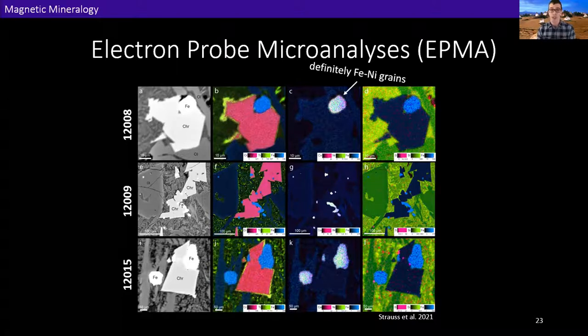I do want to highlight a few things that we noticed during these observations, though. First, we found grains with different iron-nickel ratios within each sample, and we were able to identify both kamacite and martensite in this total collection of grains. In fact, we were mostly finding martensite, which is a slightly higher nickel content than kamacite. We also saw that many of these iron-nickel grains are not homogeneous. So in this figure, you can see some compositional gradients across a few, but not all, of the grains that I'm showing. There are color differences across the grains.